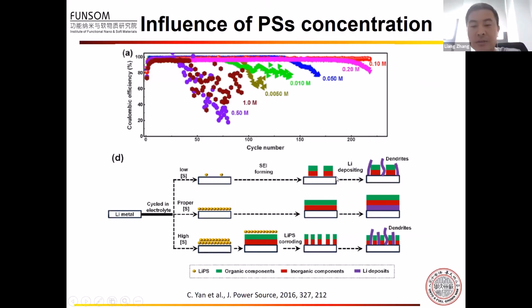In addition, the concentration of the lithium polysulfide can also influence the cycling performance. If the concentration of the polysulfide is too high or too low, it cannot form a complete protection layer on the lithium anode.